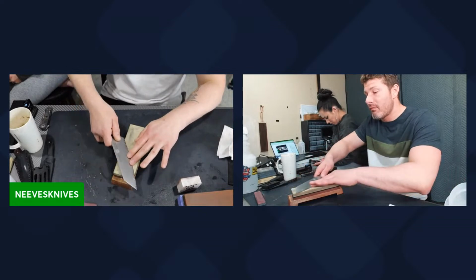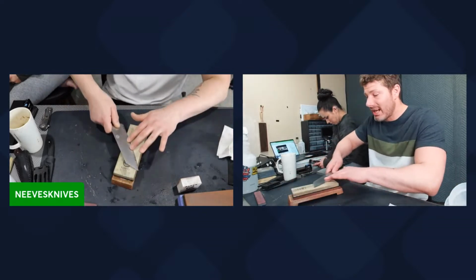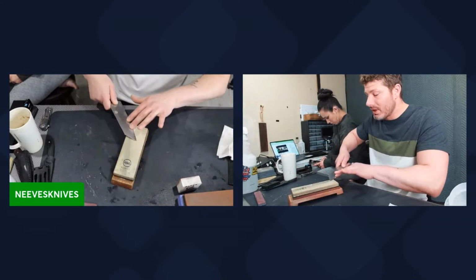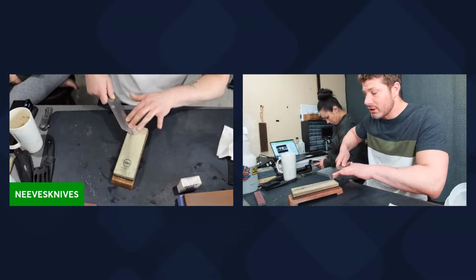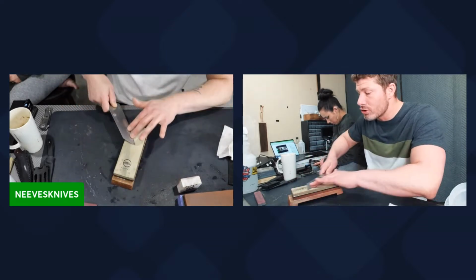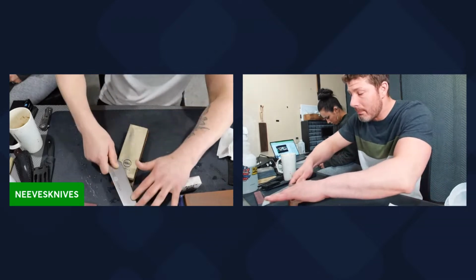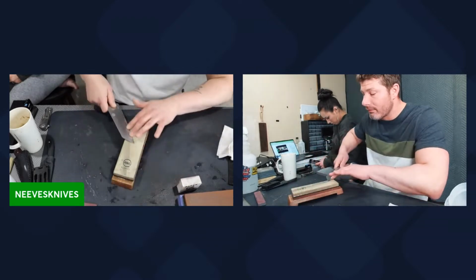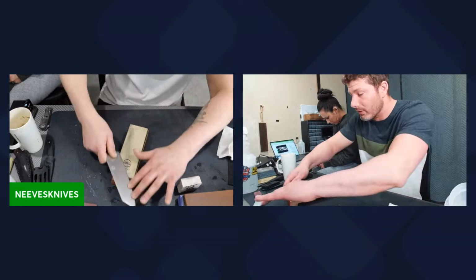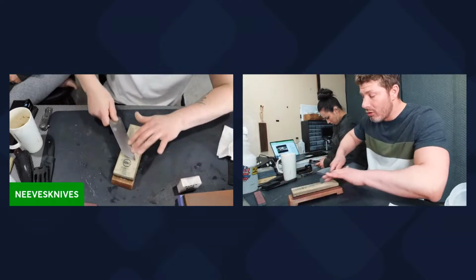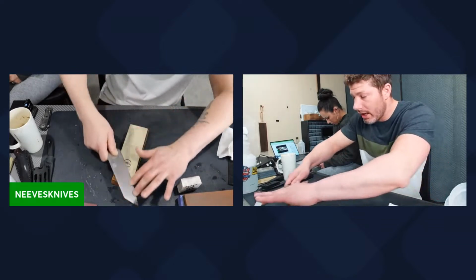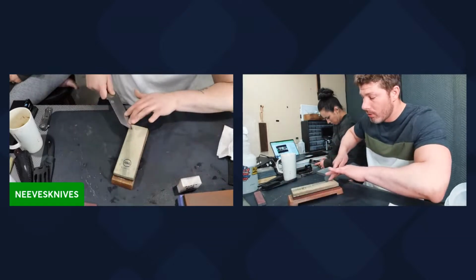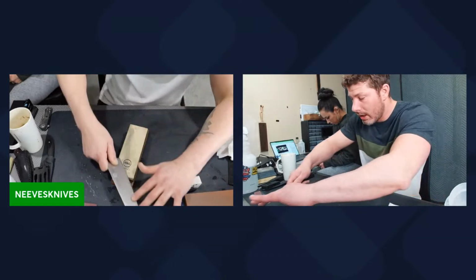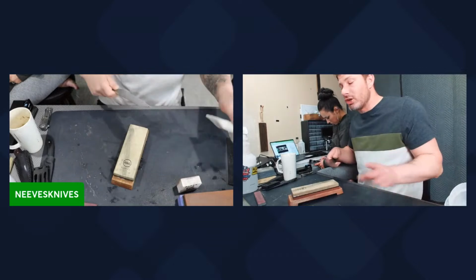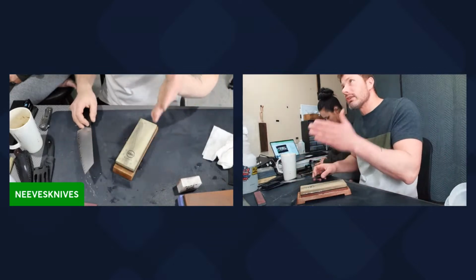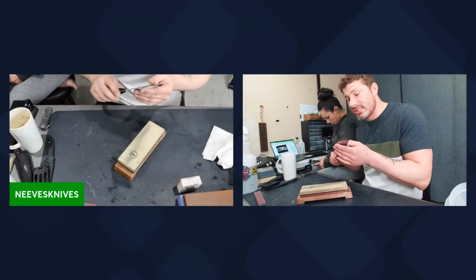You're not going to have that incredible edge retention that Maxamet has, because what will happen is you're going to remove the steel from around the carbides, and there's so many carbides that they'll be hanging out of every surface of the edge bevel, just pouring out of it, waiting to crack, shatter, and tear out. So that's why you want to do it with diamonds, so that you also cut the carbides instead of just the steel around them.